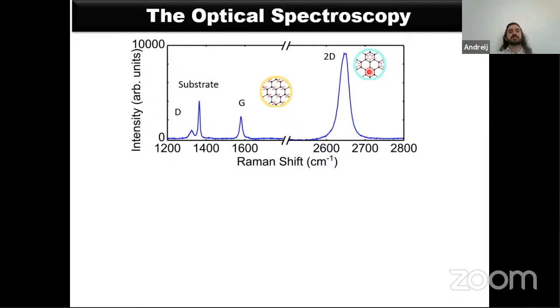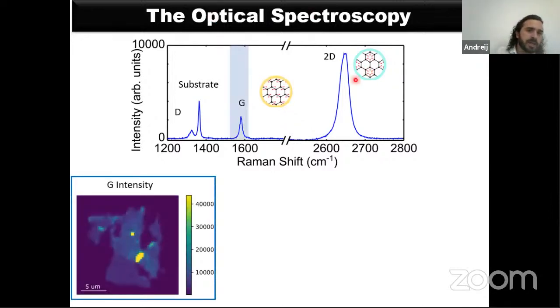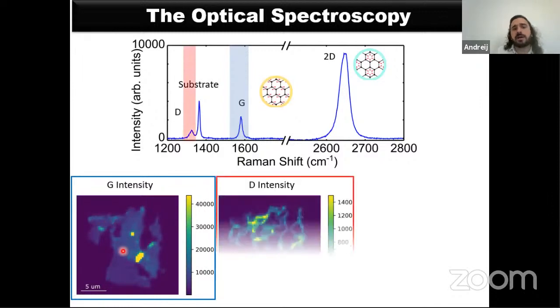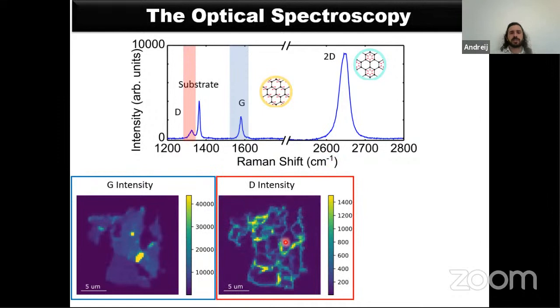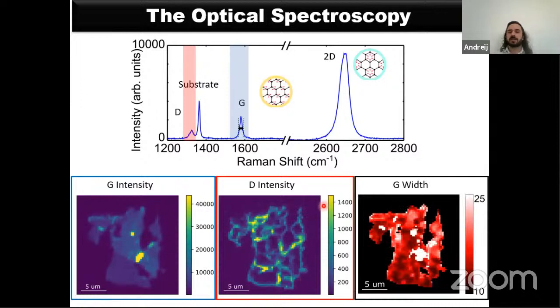And we can also do images from these peaks. For example, we can do an image from the G intensity, and so we can map, we can see where our sample is, and we can see some details inside the sample. We can also make images from the D intensity, and we can see where in the sample there are defects. For example, here they are located at the edges. And we can finally plot the G width, which is related to the coupling between the electrons and phonons. So we can see where the electron phonon coupling is located in space.